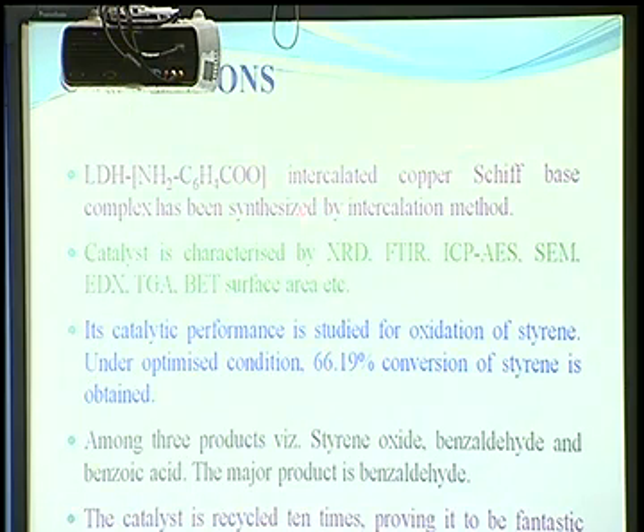Now conclusions. LDH intercalated copper Schiff base complex has been synthesized by intercalation method. It is characterized by XRD, FTIR, ICP-AES, SEM, EDX, BET surface area, etc. Its catalytic performance has been studied for the oxidation of styrene, in which 66.19% conversion is obtained.